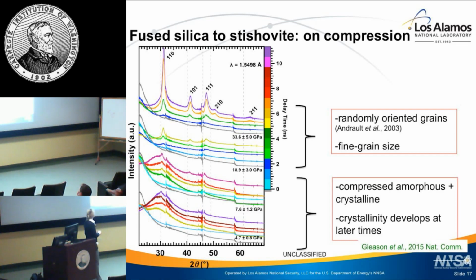For the lower pressure, 7.5 to 5 GPa, initially, early time delay, we see a superpositioning. So first, our diffuse signal from the ambient condition glass, it's compressed, right? So we see a shift in this diffuse signal, and then at later times, so red to pink, somewhere 9, 10 nanoseconds, we see now a superpositioning of the stishovite on or in tandem with the compressed diffuse signal. So this is very interesting. 2 different things going on here. The data quality are quite good.